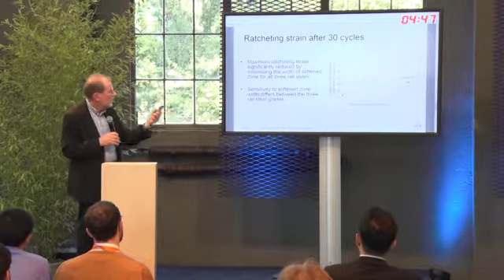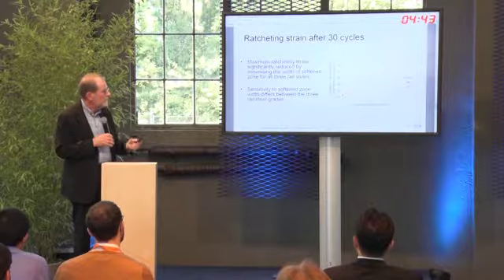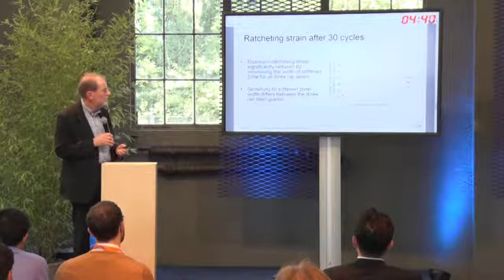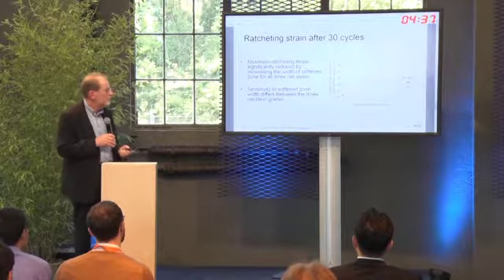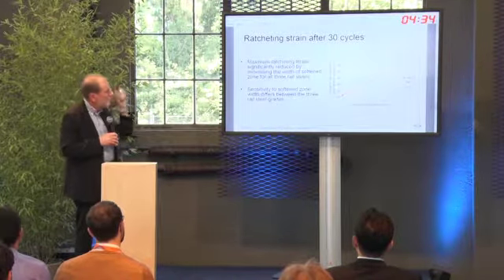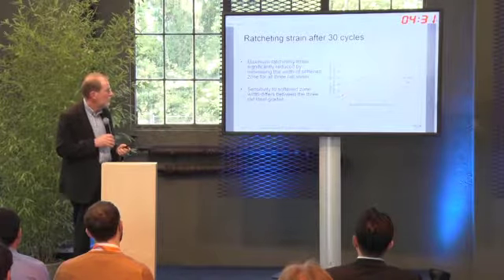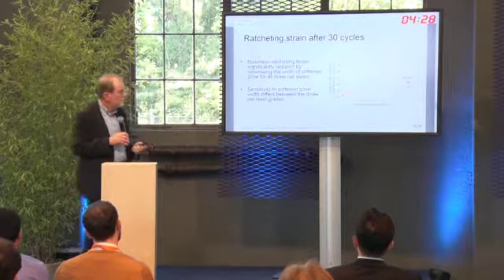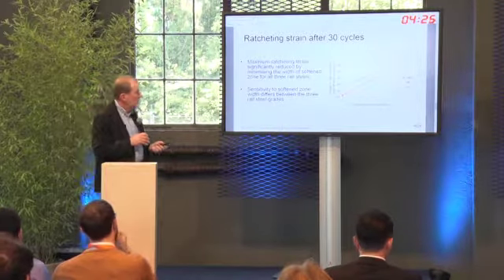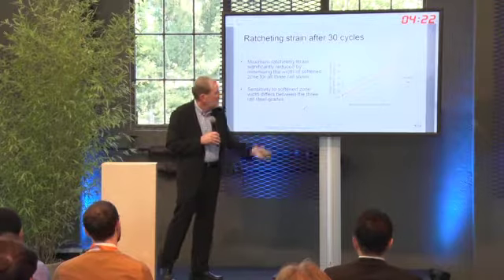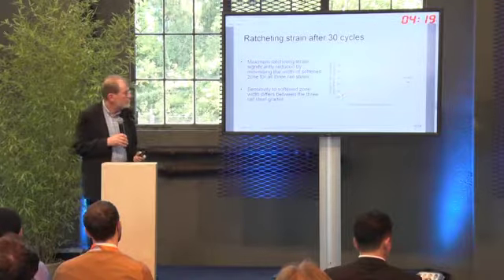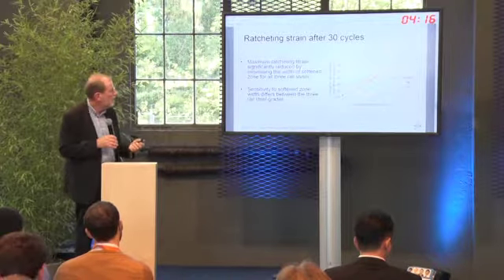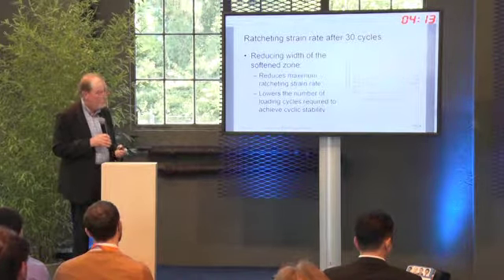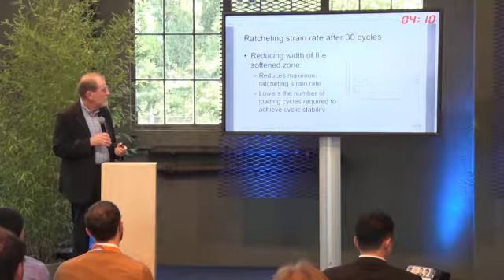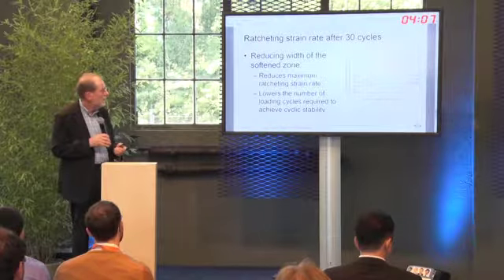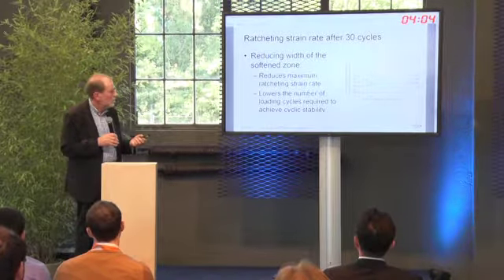If we look then at the results, which are in detail in the paper, for the width of the softened zone, as you'd expect, you reduce the width of the softened zone, the amount of strain after 30 cycles drops right off. There is, again, a bit of a difference between the three rail grades, with the low alloy one perhaps having the highest sensitivity to the width of the softened zone. The last graph shows the width against the strain rate, with a similar trend. So that's the extent of the work we've done to date with the modelling.